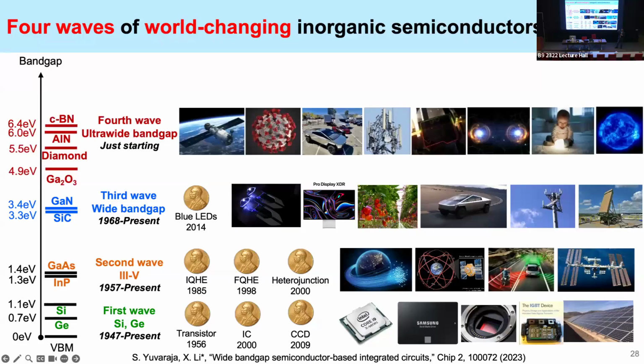So moving above, we have the ultra-wide bandgap semiconductors, right? They are represented by gallium oxide, diamond, aluminum nitride, and cubic boron nitride. Because of the much larger bandgap, they can have a much better power and RF capability compared to even wide bandgap semiconductors. In addition, photonically, because they have a much larger bandgap, people can make photonic devices well into the UV and deep UV regime, right? So that has played a very important role in combating the COVID pandemic because people can use UV LEDs to disinfect surfaces, air, and water. In addition, the very large bandgap can act as a host for quantum photonics devices as well. So there are a lot of important applications related to ultra-wide bandgap semiconductors.